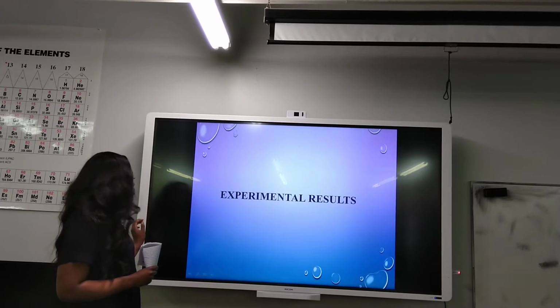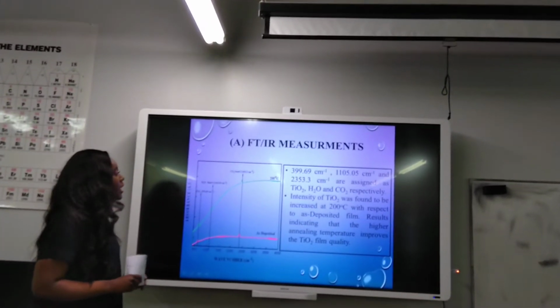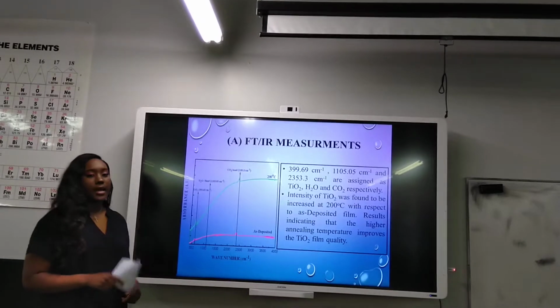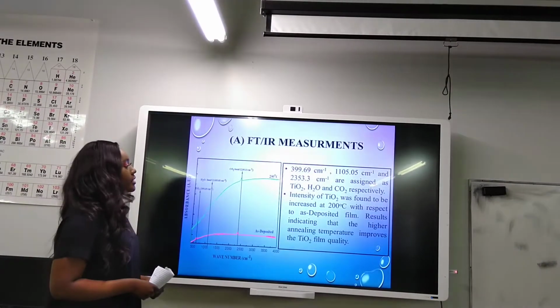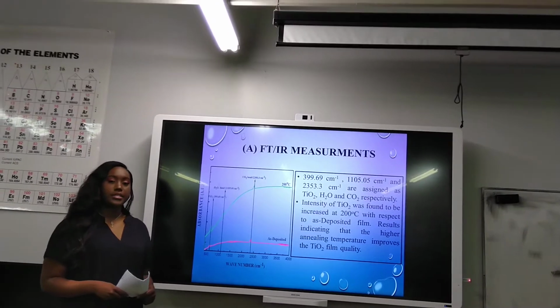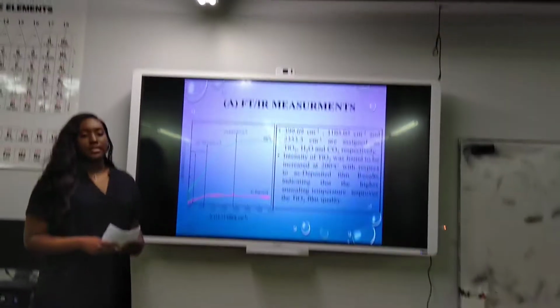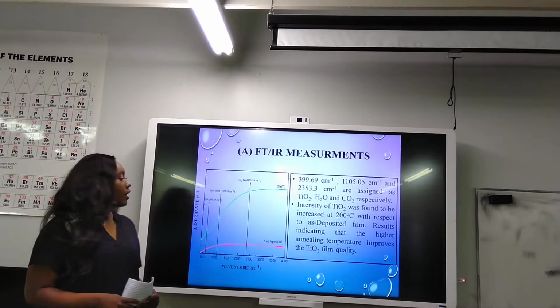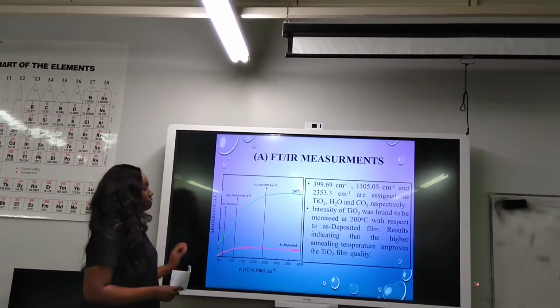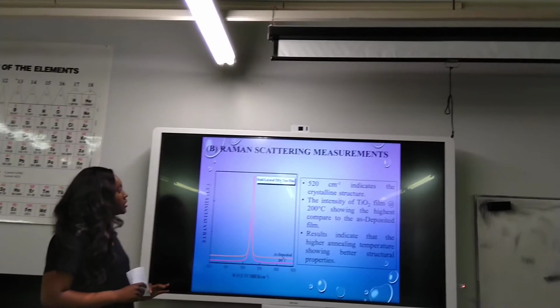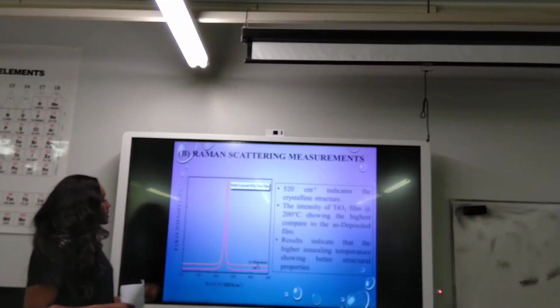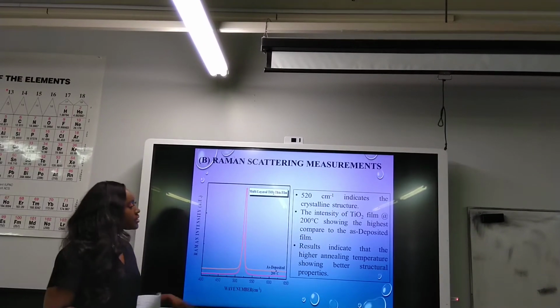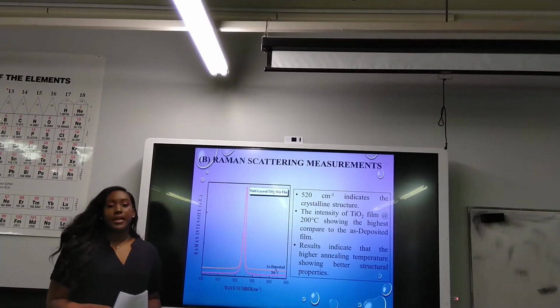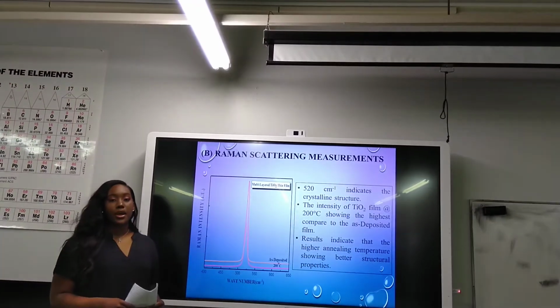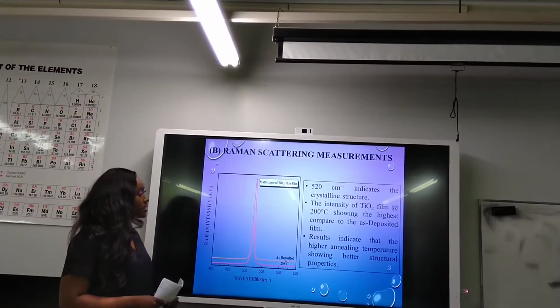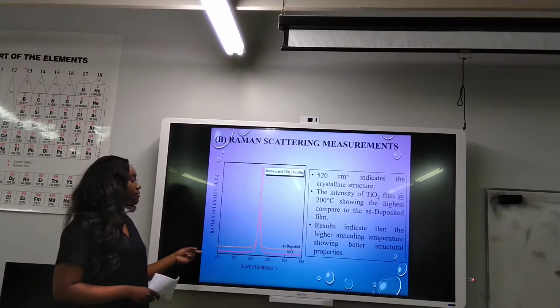So these are the experimental results. So the FTIR measurement, this is basically telling us that TiO2 is present, and the intensity of titanium dioxide increased at 200 degrees Celsius, which means that the higher annealing temperature improved the quality of the film. So this is the Raman scattering measurement, and since the lines are at 520, this indicates the crystalline structure. It is also proving that the higher annealing temperature has a better structural property than the as deposited film.